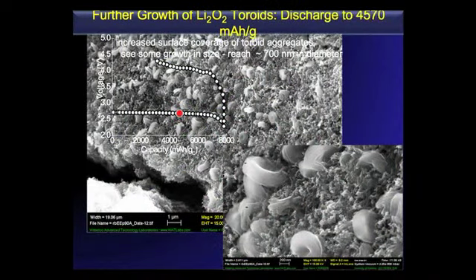And this is further along the curve where you can see quite a field of these toroidal aggregates, again, literally coming out of the carbon surface. And these don't really grow in size. They start off at about 500 nanometers, and even partway through, they're still only at about 700 nanometers. So it's the number that is increasing as opposed to the actual growth of the particles. And you can see these interesting toroids, and these are actually agglomerates of tiny crystallites that are about 15 nanometers in size based on analysis of the diffraction patterns. So it's particularly interesting to consider how these form because there must be some sort of dissolution and precipitation that allows these to aggregate in this form, and I'll leave that open for the question period.